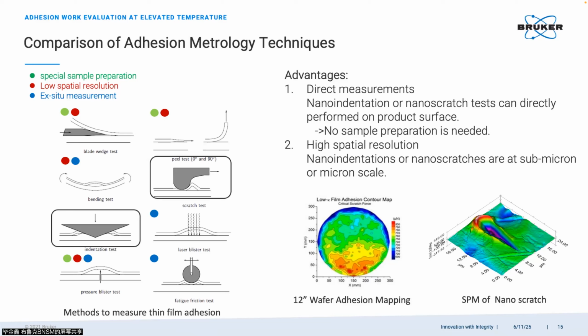So for the indentation method and scratch method, you don't need to prepare your sample. For a typical wafer, you can put your wafer in and we apply our probe directly onto your top layer to induce the interfacial debonding. So that is the very first advantage, direct measurement. The other one is high spatial resolution. A typical scratch test has a length of maybe 7 microns. That means your delamination has a very small size, and your result indicates a highly localized delamination.